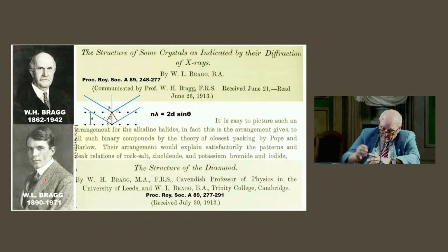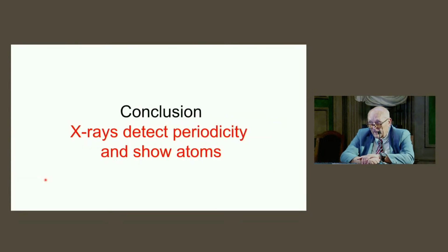How could they succeed? Having in mind what Paul Groth said, they connected the direction of diffraction, so the angle theta, with the interplanar spacing, and they measured the intensity of the diffracted rays, and were able to see that the most intense diffracted rays were those diffracted by planes where atoms were situated and so on. Anyway, I just do an excursus. Well, we can conclude that X-rays are able to detect periodicity, okay, and are also able to show atoms.